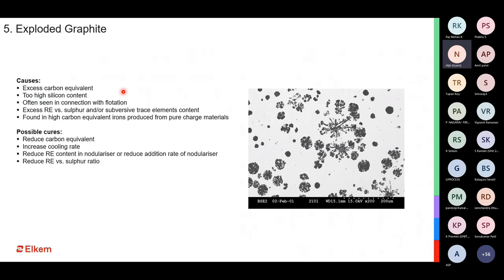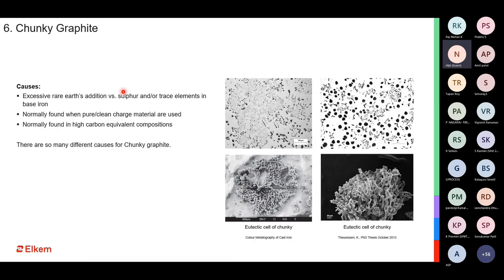How do you go for a lower rare earth? By controlling your tramp elements. Because why do you need rare earth? To control the tramp elements. So if you do not have a high amount of tramp elements, you do not need an excess amount of rare earth, and then you can produce castings without having exploded or chunky graphite in the system.